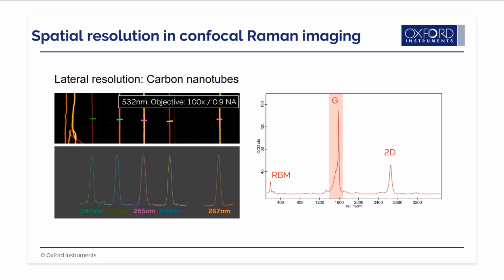Here you see the Raman image of a sample of carbon nanotubes, and here a typical Raman spectrum of the carbon tubes. The most prominent peak is the G-band shown in red here. The Raman image on the left shows the intensity of the G-band and thus the nanotubes appear bright. If we look at the profile through this image, we can calculate full width half maximum for each nanotube, providing a good measure of resolution. Our example here reveals a lateral resolution of less than 300 nanometer.